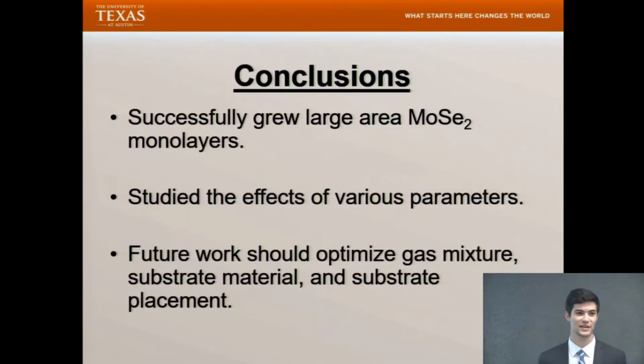So in conclusion, I had great success in growing molybdenum diselenide monolayers using chemical vapor deposition, and I was able to develop an optimized recipe. I also determined the effects on growth of various parameters, and these findings could contribute to future research in this area. And in terms of future work, my recipe could be further optimized by tweaking the gas flow rates, the substrate material, and the substrate positioning within the furnace.